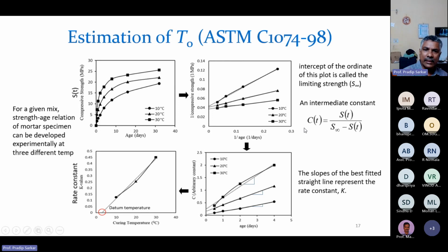This is what is CT, and from the CT, this arbitrary constant is calculated here. The intercept of the ordinate of this plot is called the limiting strength, S infinite, and ST is the compressive strength. Here you can see on the y-axis ST divided by S infinite minus ST. So this gets a C naught value, C of t. So at different time steps, we get the value of CT. And this CT versus age we consider here, and we get the slope K.